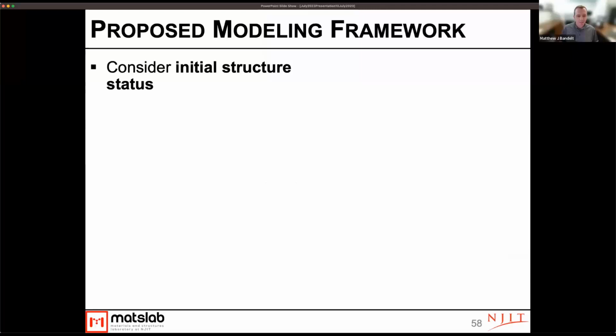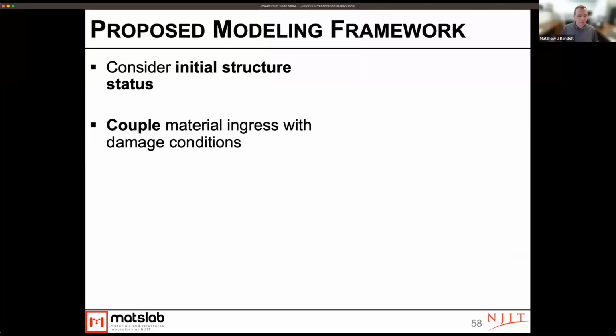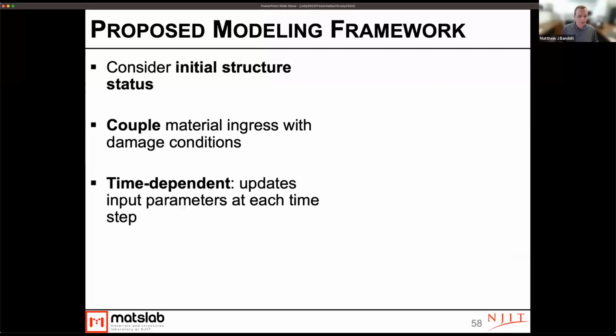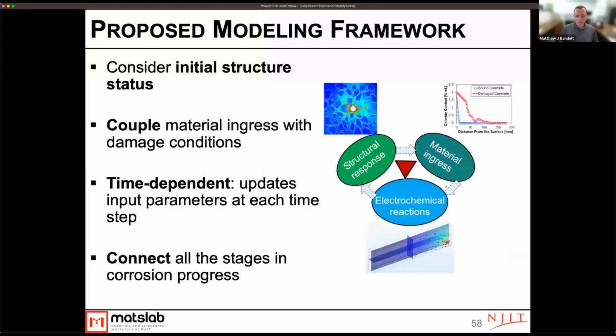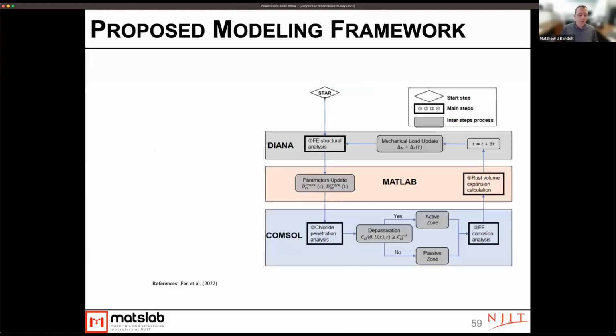And so we developed a modeling framework where we considered the initial structural status. We coupled material ingress with damage conditions. It was time dependent, and so parameters were updated at each time step. And then we connected all stages in the corrosion process. And so through this, we went through and looked at structural response, material ingress, and then the electrochemical reactions as well. This involved basically using 3 pieces of software.